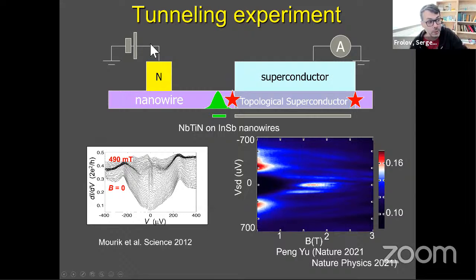So we apply voltage to this non-superconducting contact. Electrons have to hop over the barrier, tunnel through the barrier, and then they're drained through the superconductor where we measure current. So that's a circuit, and so it's a tunneling transport measurement, current voltage measurement, but we always plot conductance. So here on the left, it traces our conductance.